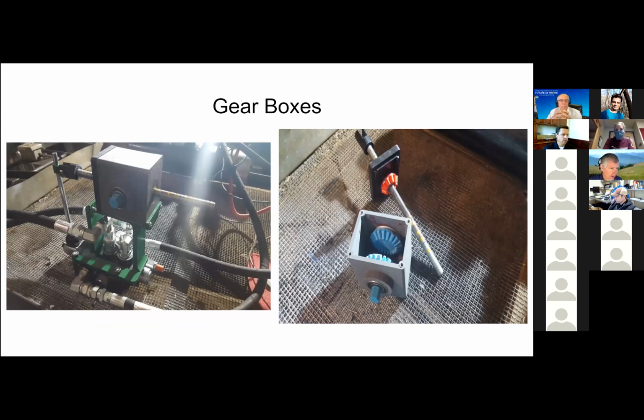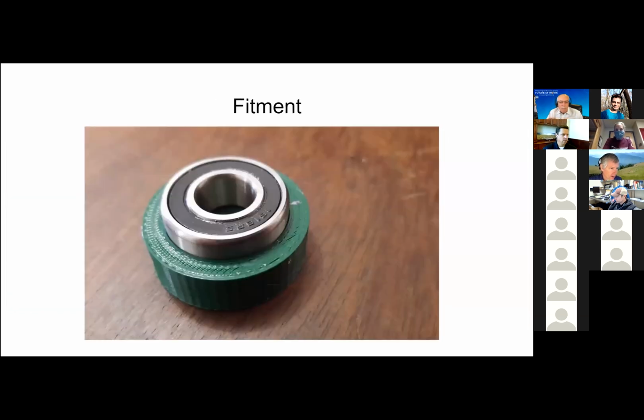When it came to large prints like the gearboxes and gears, we set the slicer to the thickest layer height, which is 0.30 millimeters. I have learned it shortens the print time considerably, with practically the same results. The gears are quite accurate and work quite well for being plastic. And the ones you see in that linear actuator, I've had up to 2,000 RPM, which is pretty fast, without wrecking the gears. I found it necessary to create little half-hour test prints for fitment, and nothing's more disappointing than realizing on your 25-hour gearbox print that the bearings were either too loose or too tight.